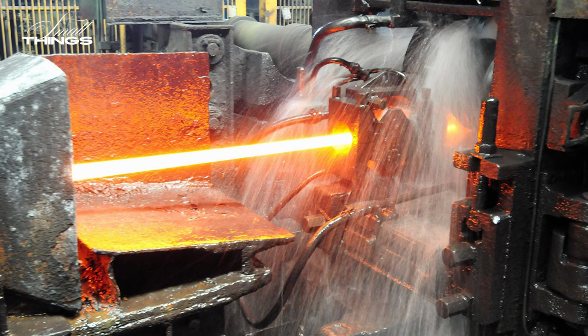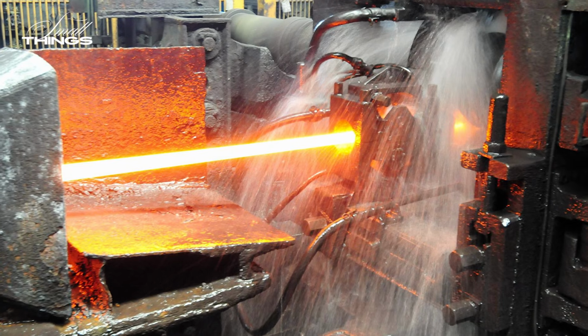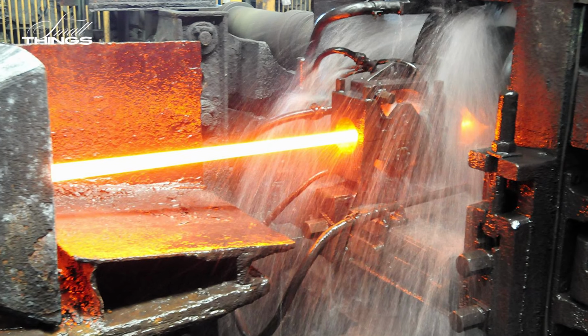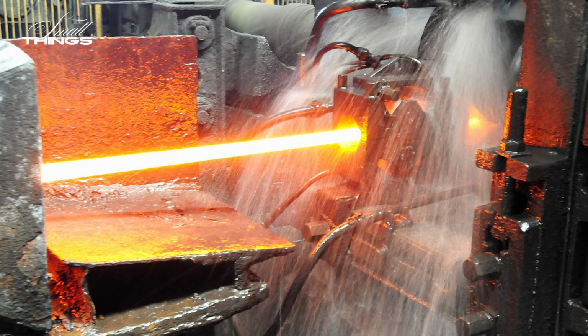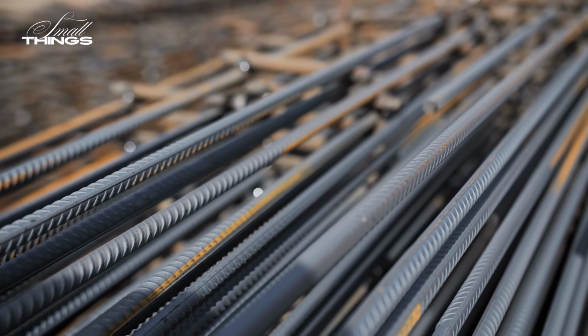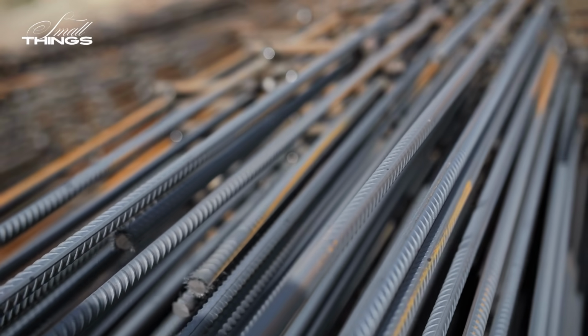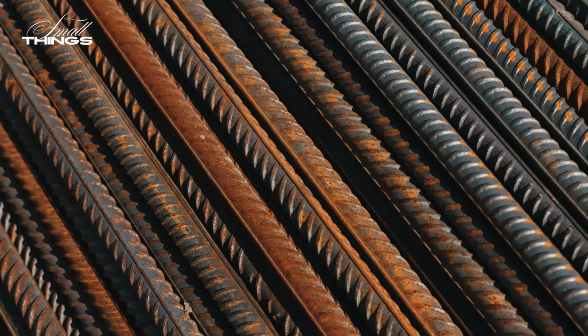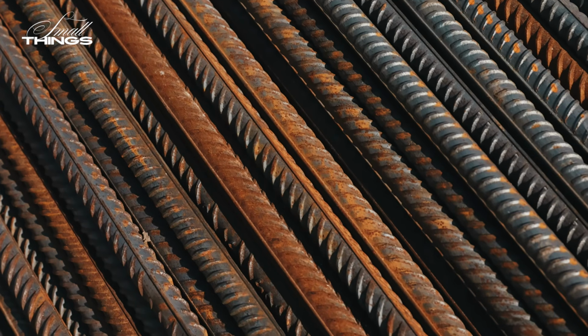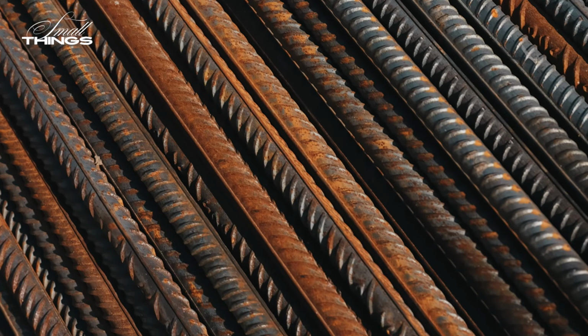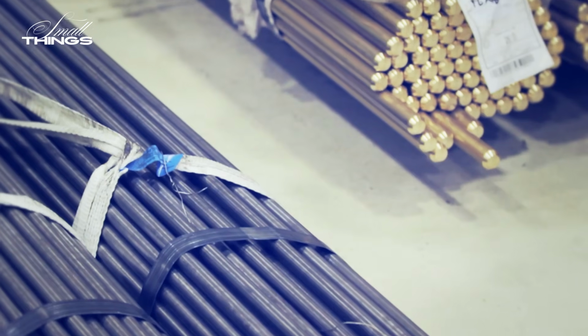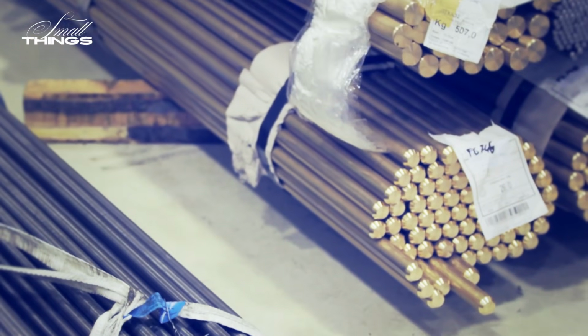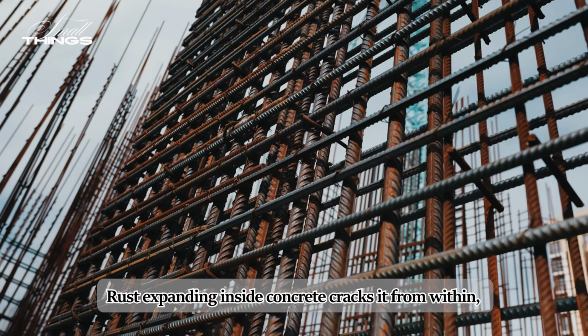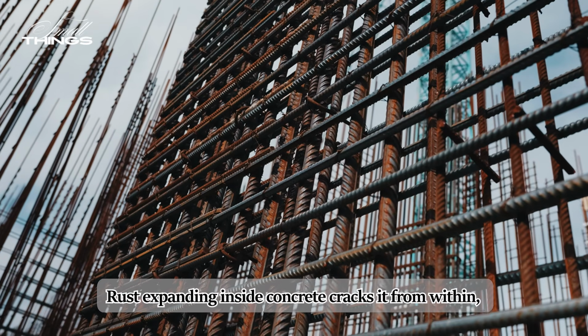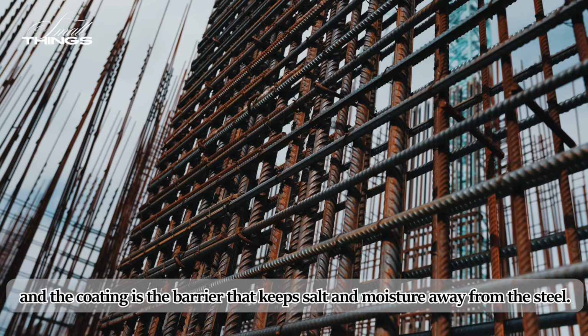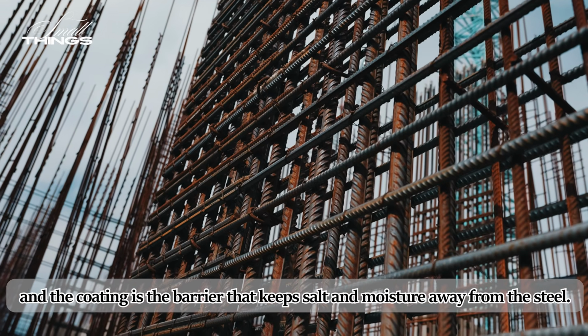After rolling, the bar passes through a water quench, a rapid cooling that hardens the outer layer while leaving the core more flexible. This combination gives modern rebar its ability to carry tension without snapping under sudden load. In environments where steel would corrode, such as coastal bridges or roads salted in winter, rebar is coated in epoxy or galvanized zinc. Rust expanding inside concrete cracks it from within, and the coating is the barrier that keeps salt and moisture away from the steel.